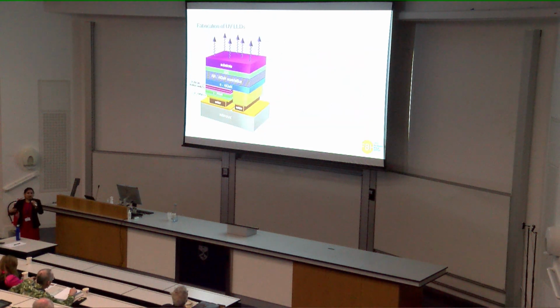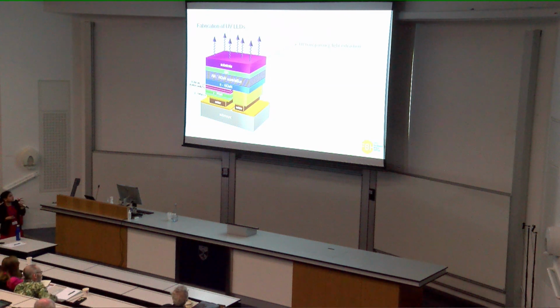And to understand why we have these low efficiencies, you need to look at the LED structure. And over here we have a schematic of a UV LED with the different layers in such a structure, and you start normally with a substrate on which you grow the different semiconductor layers. And here you can use aluminum nitride or sapphire, which is what we use in our case, and it needs to be transparent because that is where you're going to extract the light from the LED in the end.